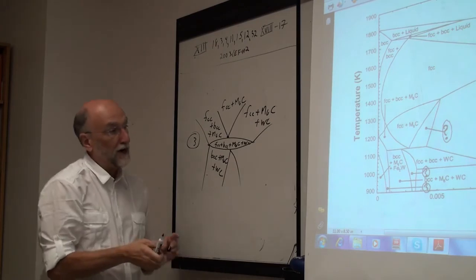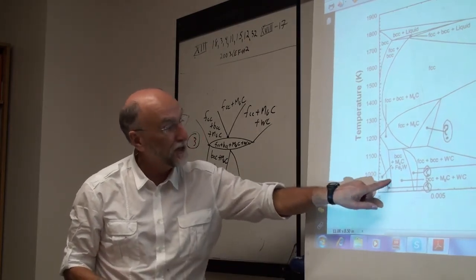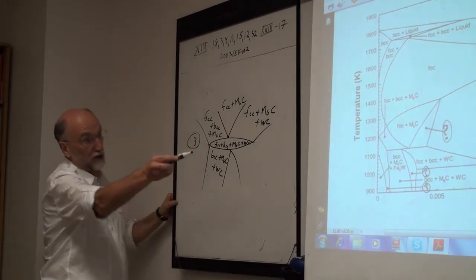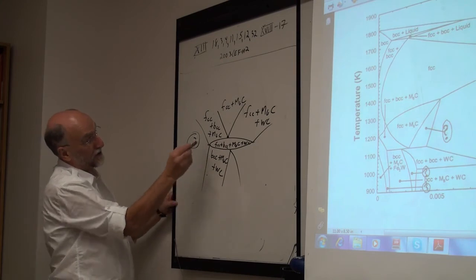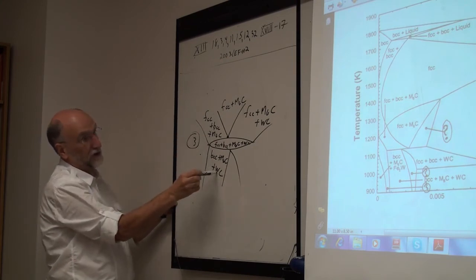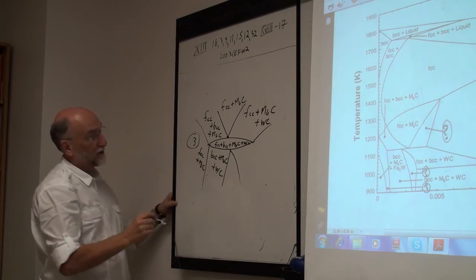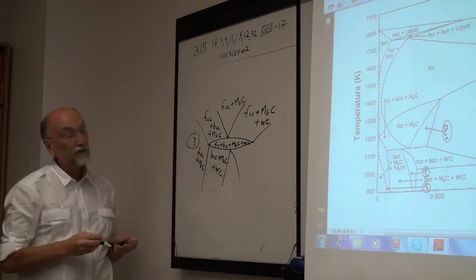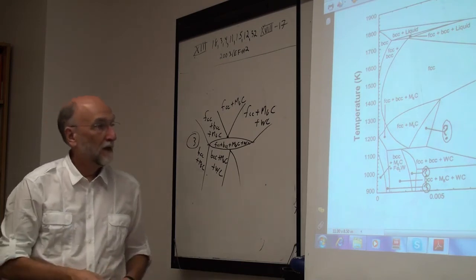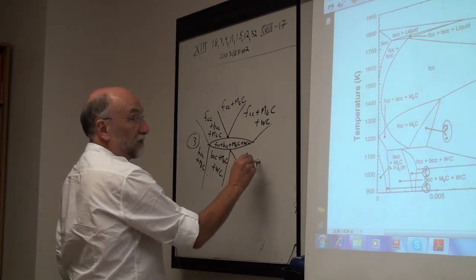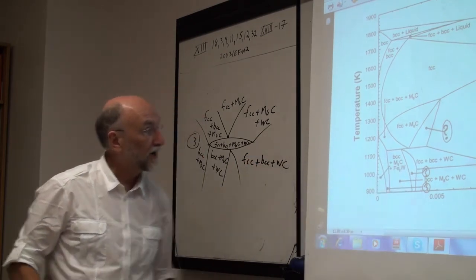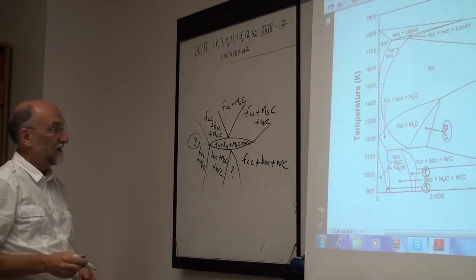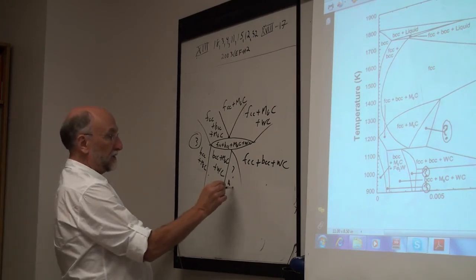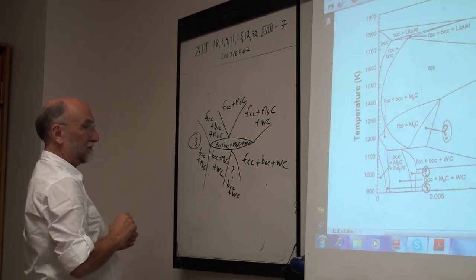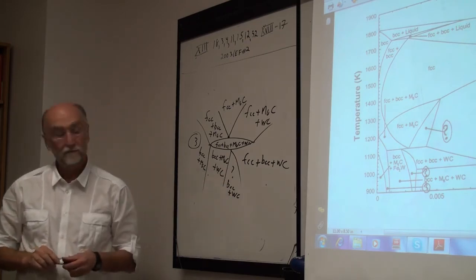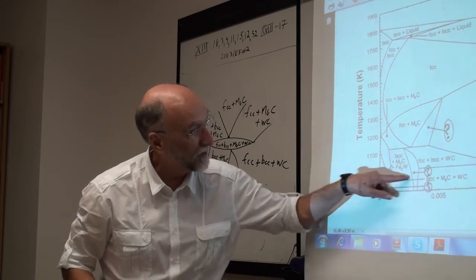Okay, now I tried to find region number 3 before by using the law of adjoining phase regions, and as you pointed out, there are 2 possible solutions. But if you look at this here, then clearly this is the 2-phase region, 3-phase region, 4-phase region. So this region must be BCC plus M6C. And then over here, you have FCC plus BCC plus WC, and so the final question mark phase here is clearly BCC plus WC. Which you can also get from the law of adjoining phase regions going across this.